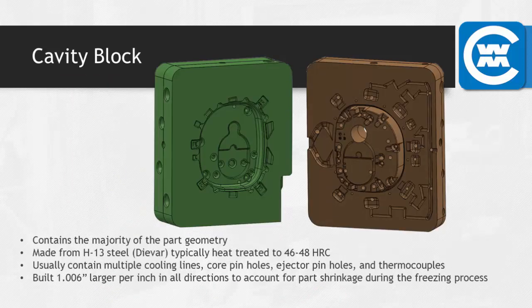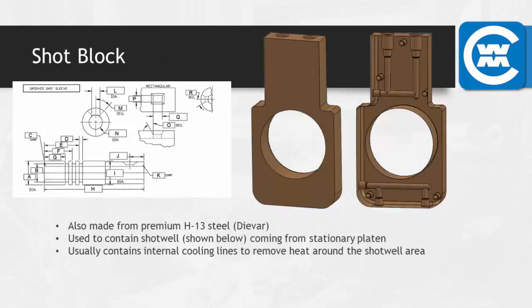Probably the most important piece of the die-cast tool, the cavity block creates the final geometry of the part. They're made from premium H13 steel, hardened to 46 to 48 Rockwell. Contain cooling lines, oil lines, thermocouples, core pins, ejector pins. Because molten die-cast metal shrinks as the metal cools and freezes to solid, the cavities are built 1.006 inches larger per inch in all directions, so that when the final solidified casting comes out, it conforms to the print. Shot block contains the shot well sleeve where metal comes in from the shot end of the machine. Contains cooling lines just like the cavity steel and is made from the same material.